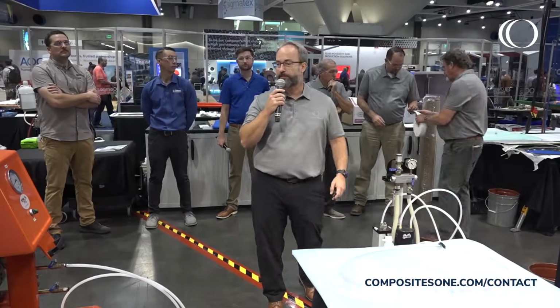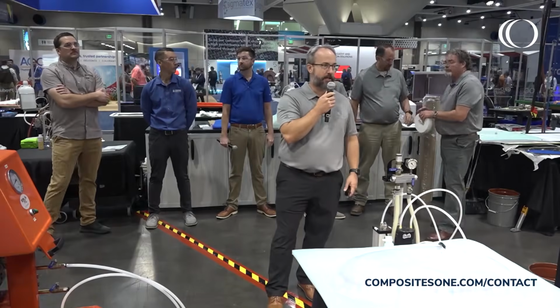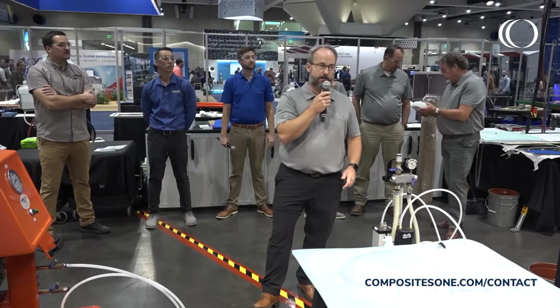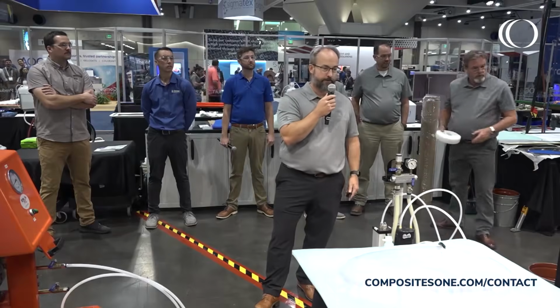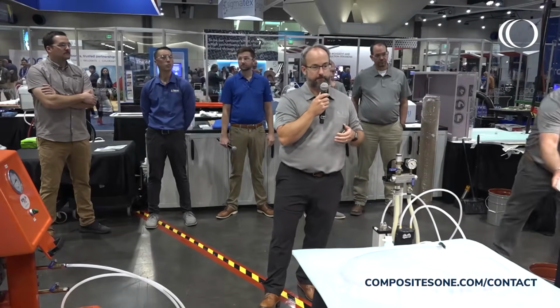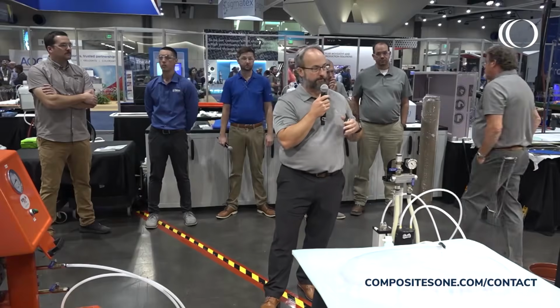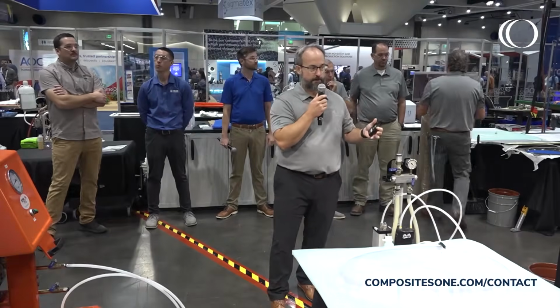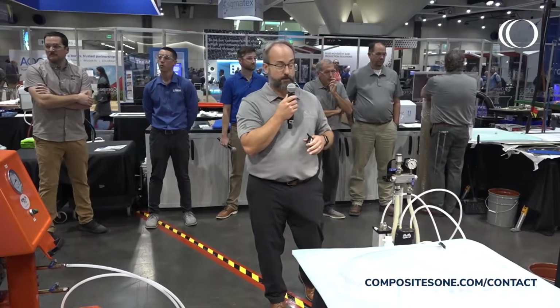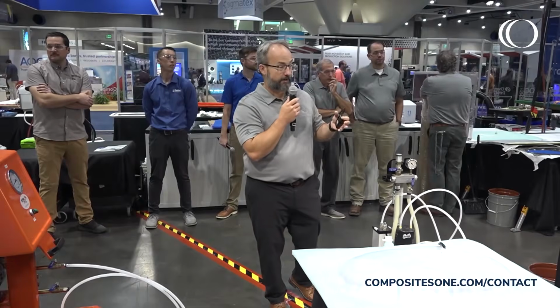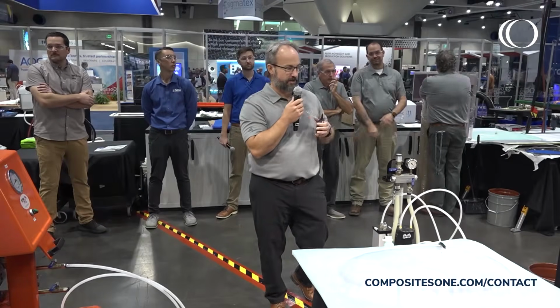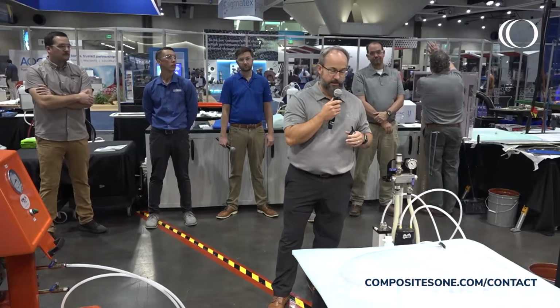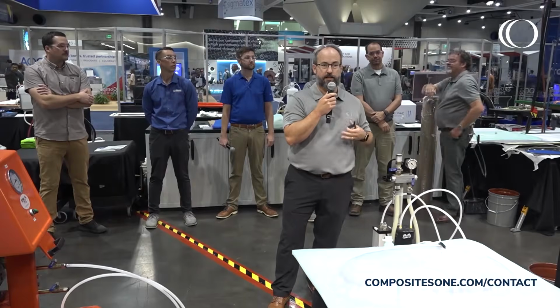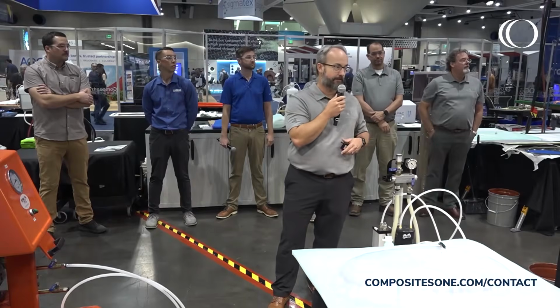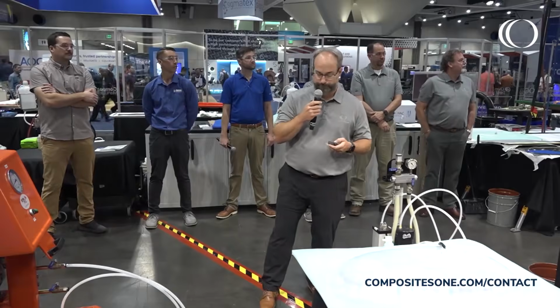The demo we're starting right now, we're going to be doing an epoxy infusion of a carbon fiber braided preform. So we're going to go through the steps of how we make the preform. We'll transfer it to our production tool, and we'll infuse the part all during the demonstration. And we have a temperature-controlled mold, so we can get a really fast cycle time on our epoxy infusion.